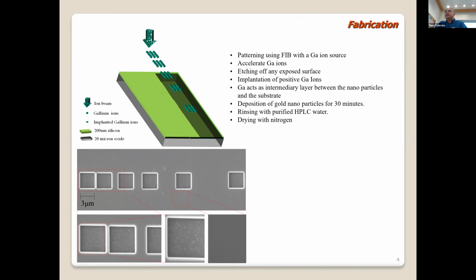We have developed a semi-mass production technique that uses microelectronic machinery to realize those devices. We mark our silicon wafer with a FIB, which causes implantation of positive gallium ions in the silicon wafer, and then we put a solution with metallic, negatively charged surfactants, metallic nanoparticles, and those nanoparticles are attracted to the position where the positive gallium ions were implanted. And after we clean our wafer, the metallic nanoparticles stay only in the locations that were marked with the focused ion beam. This is how we can bring our nanoparticle into the designed hole within which it needs to move.